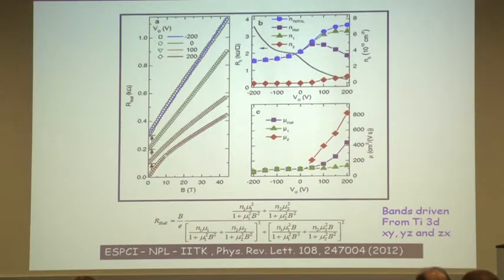So I cannot say that this is happening because of some sort of an anomalous Hall effect coming because of magnetism in the problem. These days, many people are talking about ferromagnetism at the interface coexisting with superconductivity. But our data suggests that there is no ferromagnetism. We have not seen any signatures of that. This curvature can be interpreted in terms of a two-band picture where you have two types of electrons, electrons with very high mobility and electrons with very low mobility. And if I put that in the two-band formula, I can extract the mobilities of the high mobility carriers, mu 2 here, and the low mobility carriers here, and these are the corresponding carrier densities.